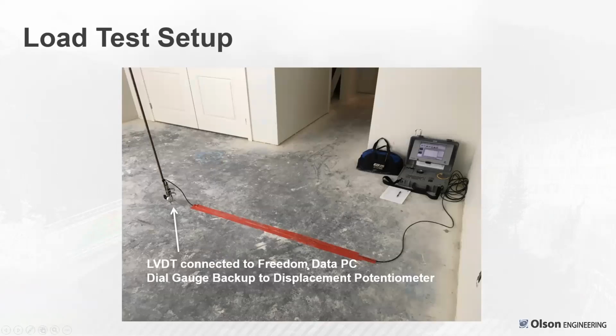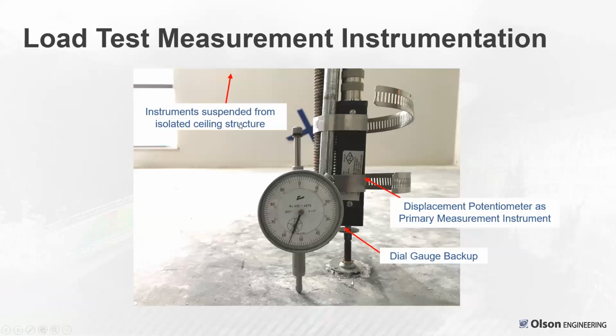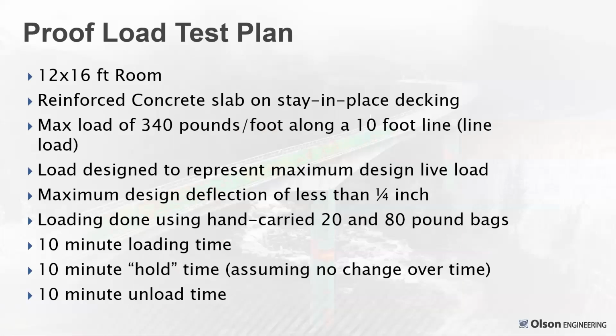It was basically a displacement potentiometer type approach connected to the Freedom Data PC, a module for that, with a dial gauge at the bottom. And there's a blow up here. The instruments were suspended on a rod from the isolated ceiling above. And the displacement potentiometer was the primary measurement instrument, but we had a dial gauge as a backup. In case something went wrong with the instrumentation, it shouldn't and it didn't, but it can, we could read the dial gauge. It's always nice to have dial gauges, at least to some extent.